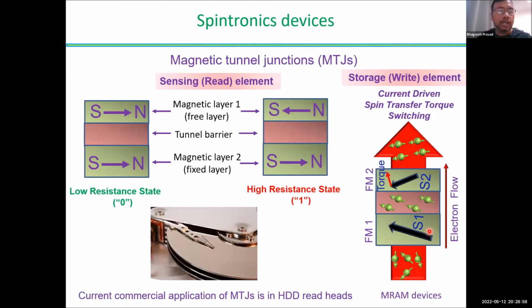Okay, now what we are actually looking for here is that we need to create highly spin polarized current through this ferromagnetic metal, so that your current is highly spin polarized, and you have effective spin angular momentum transfer to this other layer. Typically we use ferromagnetic metals for this, like iron, cobalt, nickel, and the spin polarization of these systems is around 50 to 60%. If you want to transfer this spin angular momentum effectively, that means you can reduce the switching current. This is now one of the bottlenecks in STT MRAM: how to reduce the switching current. So one way to do it is if you can generate highly spin polarized current here. Can you do that by other means?